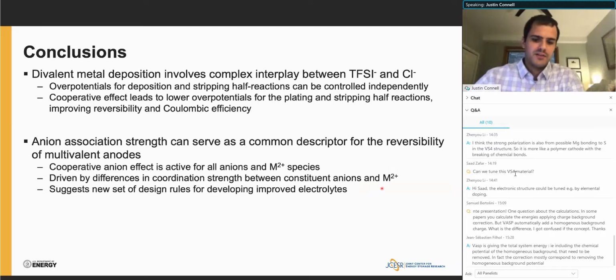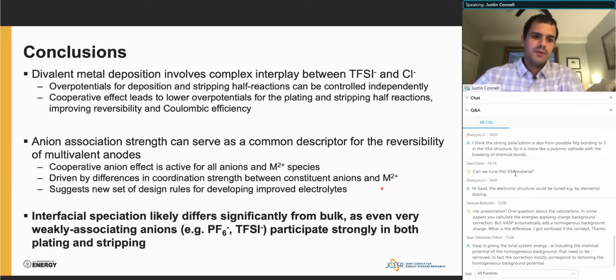And again, as I mentioned, this suggests a new set of design rules that we can use to develop new electrolytes. And the one comment that I'll leave with is that what these results seem to suggest is that interfacial speciation likely differs significantly from that we see in bulk measurements of electrolyte composition, as even these very weakly associating anions like TFSI and PF6 in particular appear to participate very strongly in both the plating and stripping reactions.